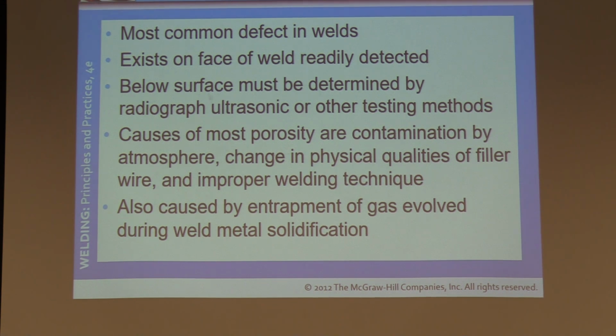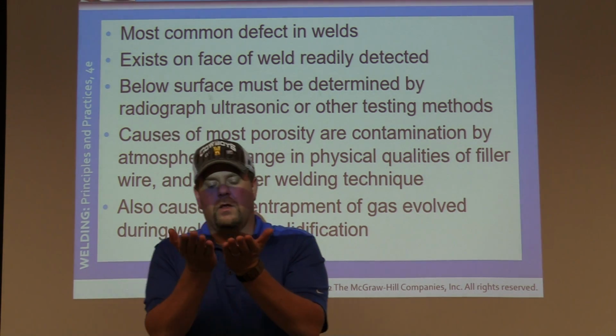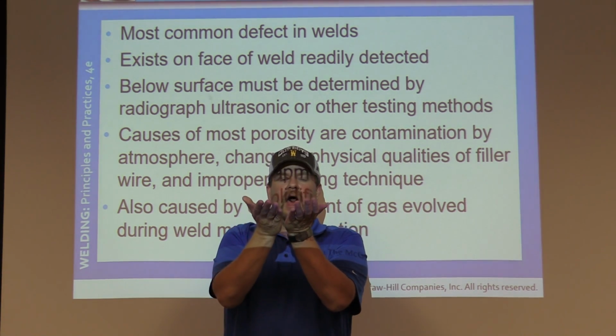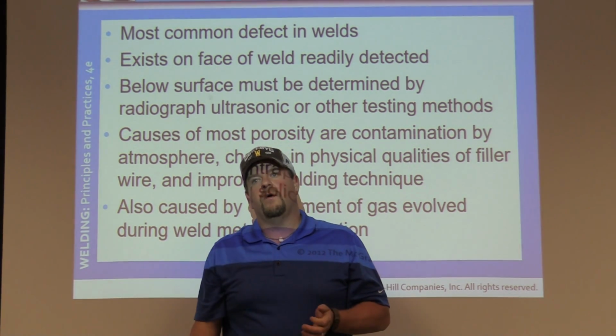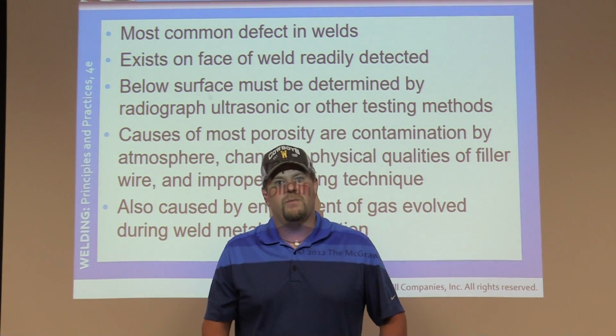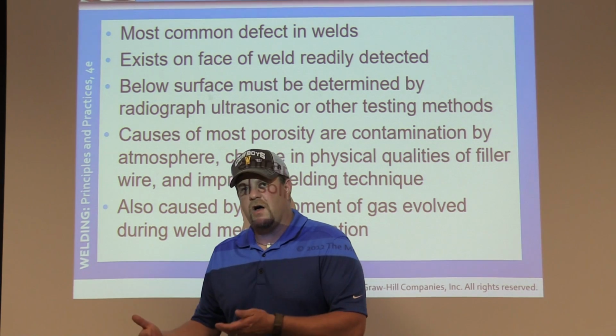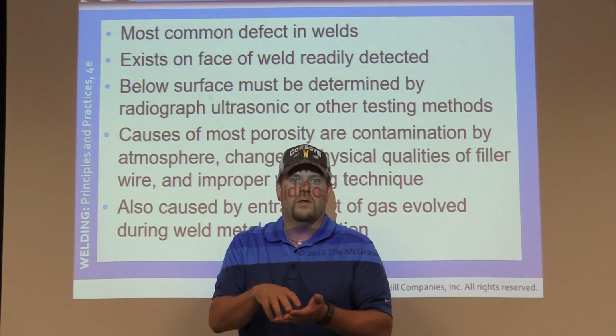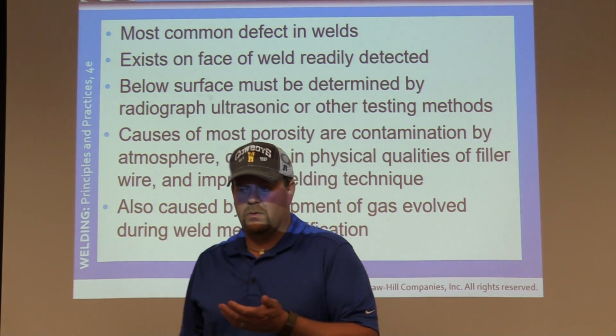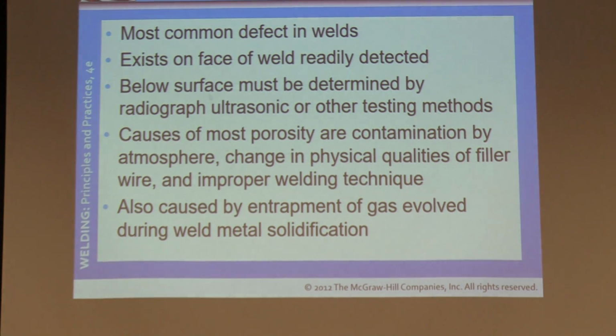Say if you don't have an open root, you're trying to weld a root on the bottom of the table. So, say you're doing an open root weld, and right below you is the bottom of a table. Your gas is going through the root and bouncing right back up at you, so you're fighting yourself. Think about that when you're doing that. A lot of times people in the booth will want to go in, they'll set it together, put it right on top of the table, try to weld it up. Well, your gas is shielding right back up in, creating more porosity in the weld. Make sure it's off the table so your gas is shooting through the root, through the backside of the weld, and not causing you any harm as you're welding this piece of material. Okay?